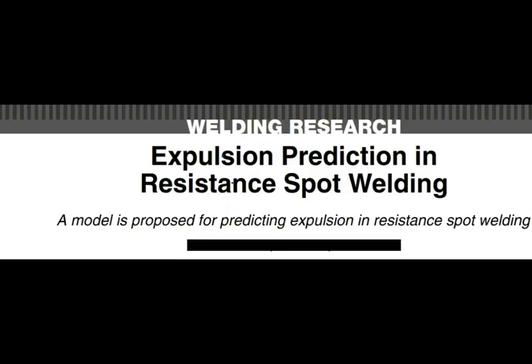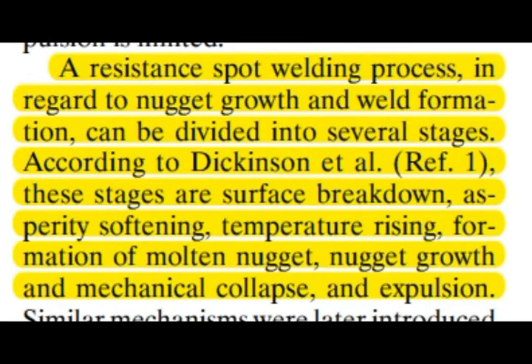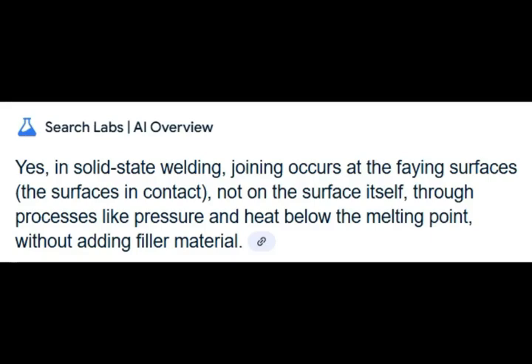A resistance spot welding process, in regard to nugget growth and weld formation, can be divided into several stages. According to Dickinson, these stages are surface breakdown, asperity softening, temperature rising, formation of molten nugget, nugget growth and mechanical collapse, and expulsion. In solid-state welding, joining occurs at the faying surfaces, the surfaces in contact, not on the surface itself, through processes like pressure and heat below the melting point, without adding filler material.